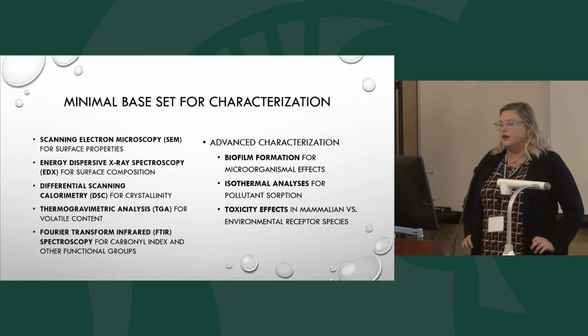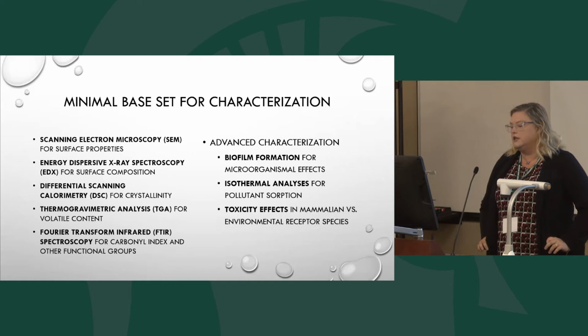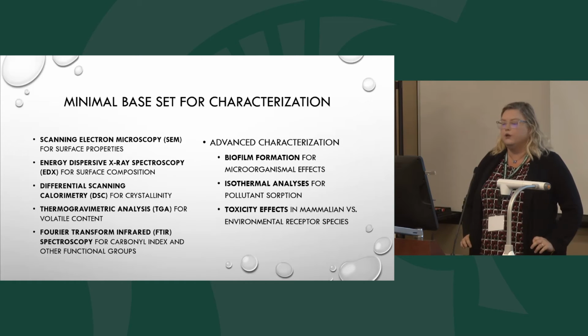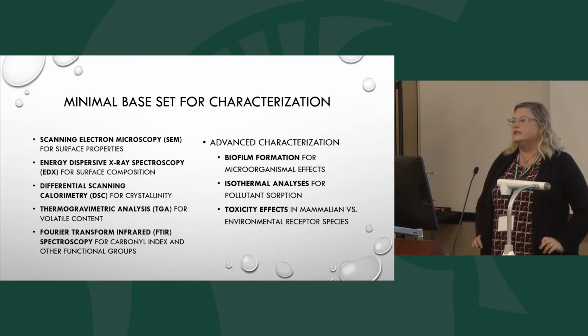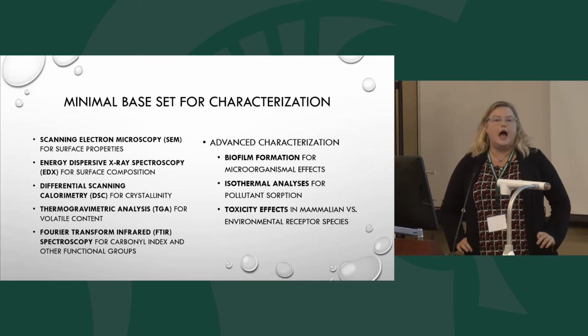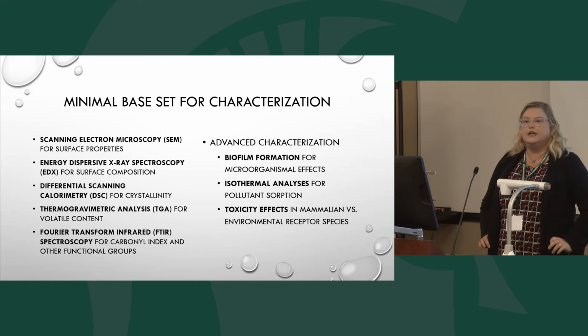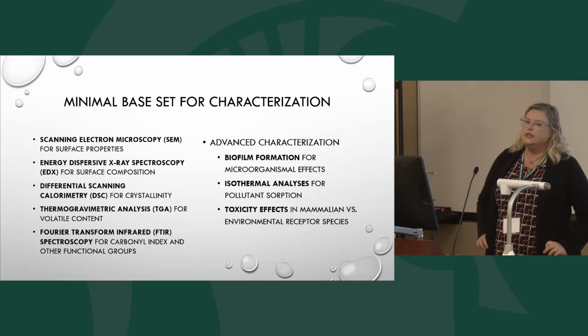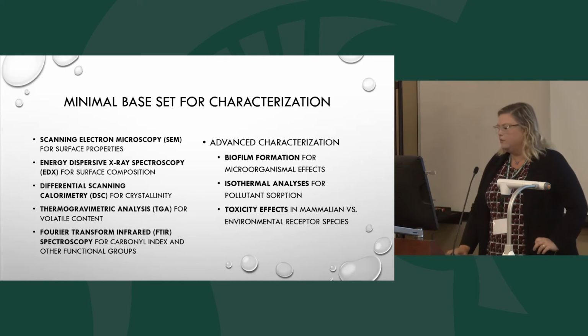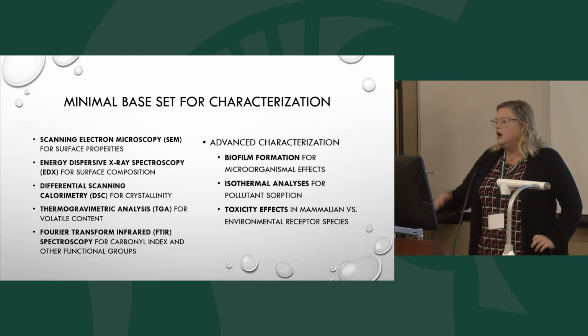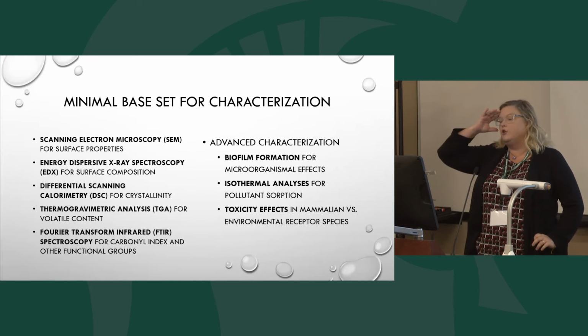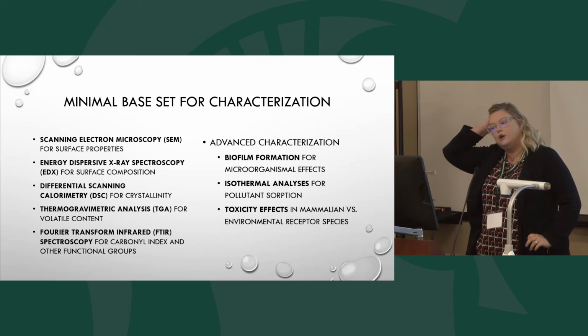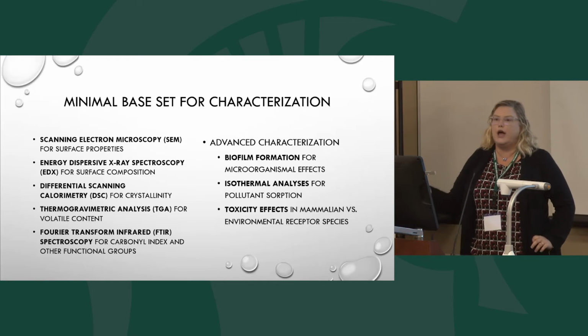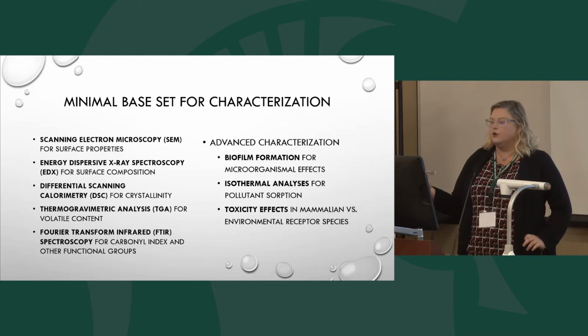TGA will help us determine the volatile content that's in the microplastics. And of course, the FTIR is turning out to be a really reliable place to get the carbonyl index, and other functional groups, but the carbonyl index is that characterization that tells you how much oxidation that microplastic experienced, either in accelerated aging in the laboratory or if you harvested it from the environment. Additional advanced characterization includes whether or not these microplastics have a propensity to form and grow a biofilm on their surface, and the isothermal analysis that I alluded to before of whether the microplastics tend to adsorb or have some sort of absorbance of other chemicals that are in the water as well.